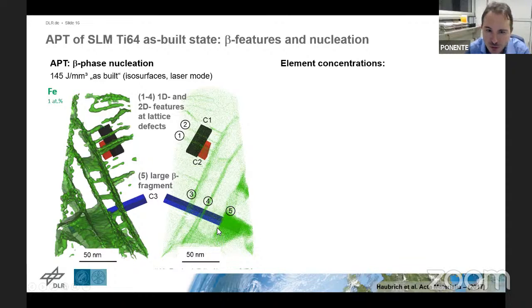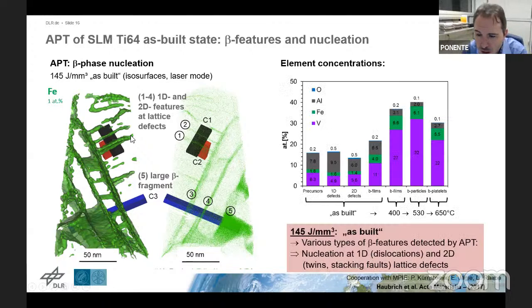And this allowed us to understand that the beta phase formation due to the heat treatments or due to intrinsic heat treatments, so due to energy input essentially, leads to formation of new beta phase along lattice defects, like dislocations, which we could confirm here with APT in our work. APT further gave us information then on the beta phase in the different conditions. Here you see on the right-hand side in the bottom axis, the different kinds of beta phases in the as-built state and the 400 up to 650 degree heat treated states.